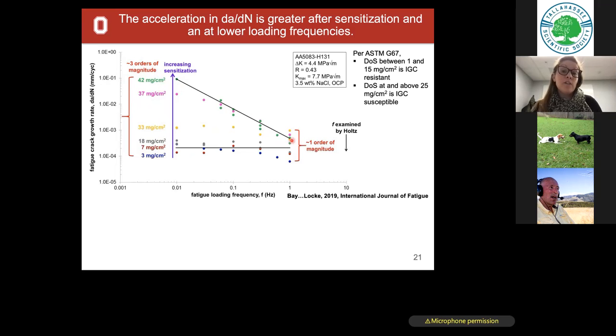In fact, the crack growth rate is increasing an order of magnitude for every order of magnitude decrease in frequency. This is more close to what a naval operational frequency would be. And what we see here is that the crack growth rate is 3 orders of magnitude accelerated over what it would be had I never baked it at all. So we're seeing what we would consider severe acceleration and damage accumulation because that material was exposed to temperatures that are slightly elevated from room temperature.